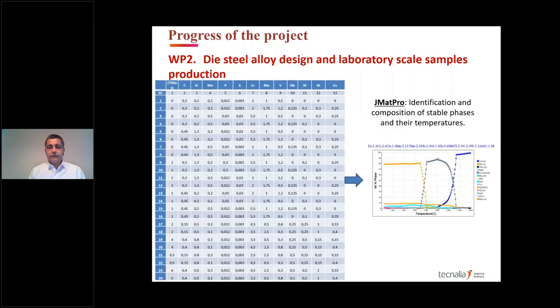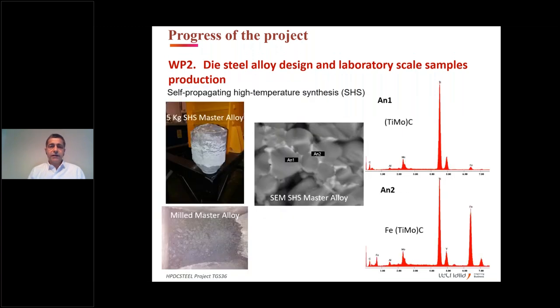So we have here the 24 alloys that we selected when the Taguchi matrix was done. It was also based on simulation. We have JMatPro and Thermocalc in the project to determine the composition of stable phases, the temperatures, and so on. And we also developed the self-propagating high temperature synthesis. At this point, we start with small batches of about 1 kilogram, and we go for 5 kilograms.